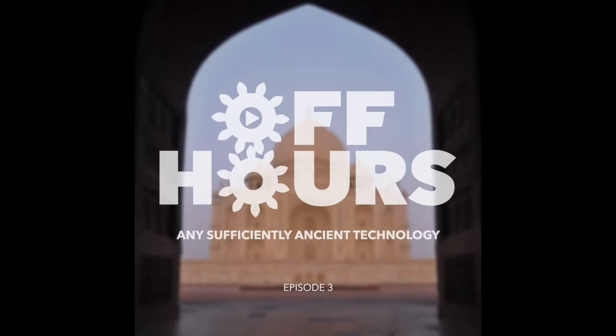Now, when it comes to other metals, the biggest issue that you get with other metals is the temperature that you end up casting them at. So in the case of silver, I'm casting somewhere around 900 to 950 degrees Celsius, which I guess works out to around 1700 degrees Fahrenheit. Most gold you end up working with is cast in a similar sort of temperature range.